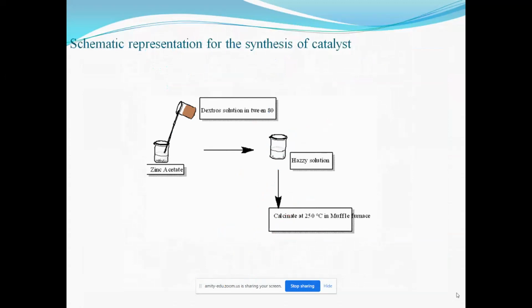For the synthesis of the catalyst, I have used zinc acetate as a precursor. This zinc acetate solution is combined with the dextrose solution in a conventional synthesis, and this solution was diluted with water, and after vigorous stirring, the solution became very hazy. Afterwards this solution was calcinated at 250 degrees centigrade in a muffle furnace.